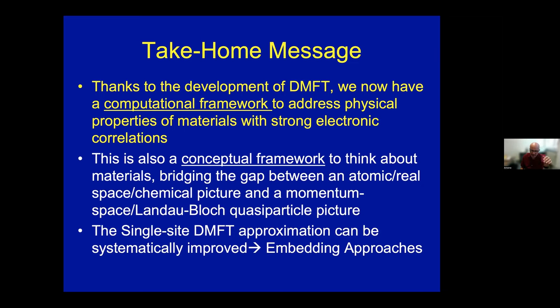So GW/RPA can be combined with DFT by treating screening from an ab initio perspective and imposing at the DMFT level self-consistency, both on sigma and on P, the local polarization. That's what we call in our jargon extended DMFT. And of course, then the physical effect would be that the insulating phase has less screening than the metallic phase. And in principle, one can calculate through the transition how this changes the nature of screening.